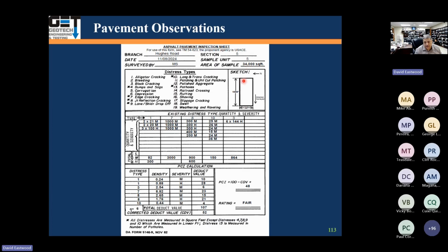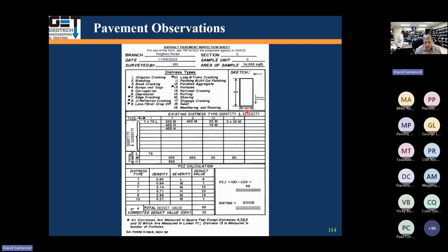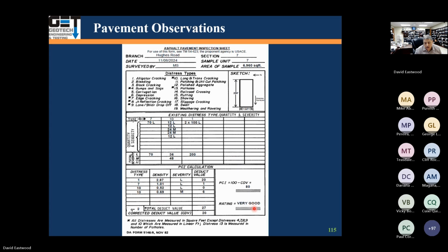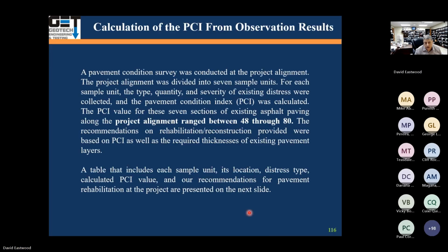Here's another segment 1,000 feet by 34 feet. And we got a PCI of 48. That was fair quality. Here's another one 28 foot wide by 500 foot long. We got a rating of 68. That means the pavement is in good condition. And then last segment, 24 foot by 290 foot long. Rating was 80. It's a very good condition, that pavement. So using the pavement rating system, we got a range between 48 and 80. So our pavement basically performed from fair to very good.